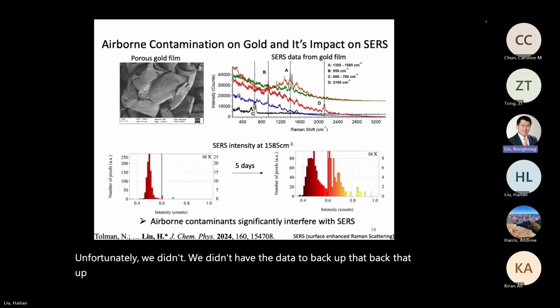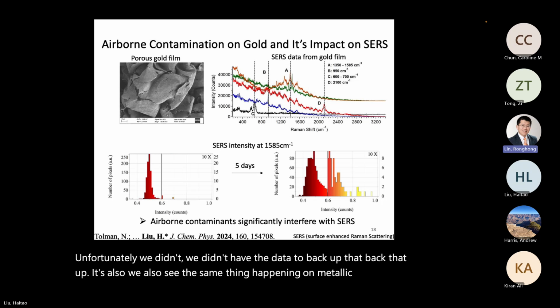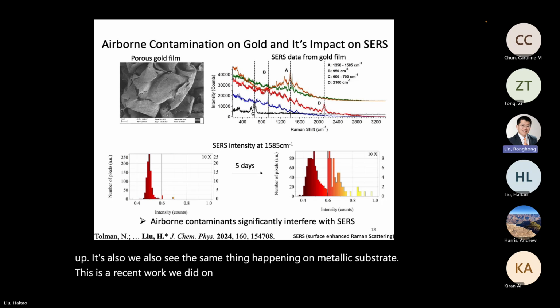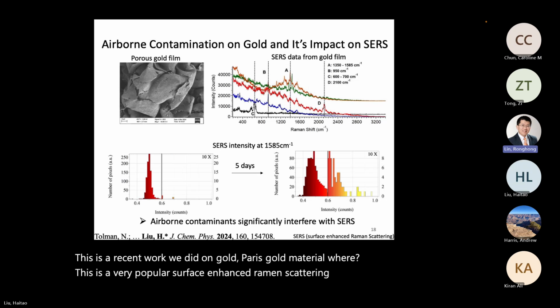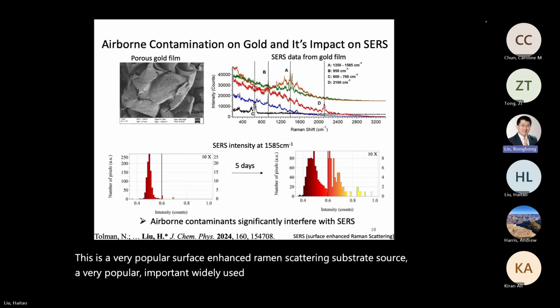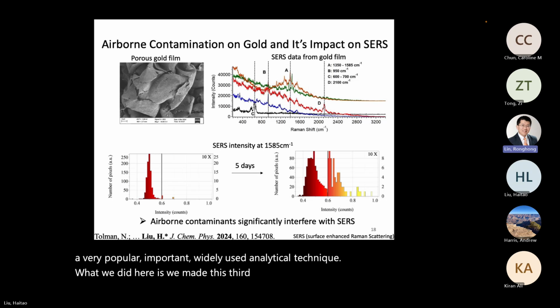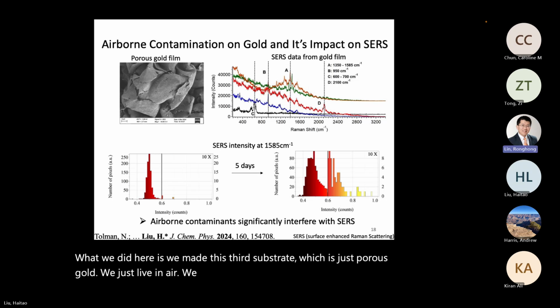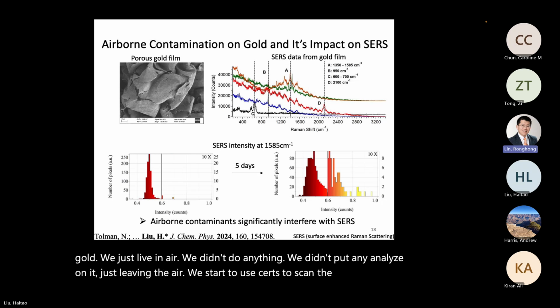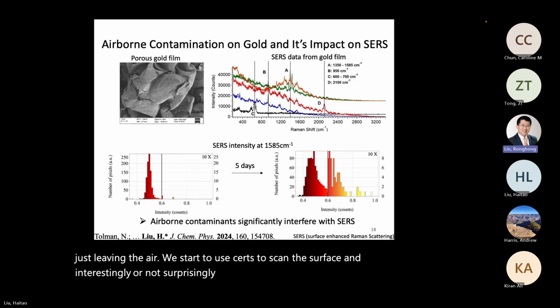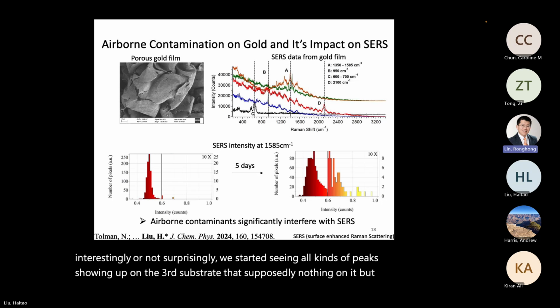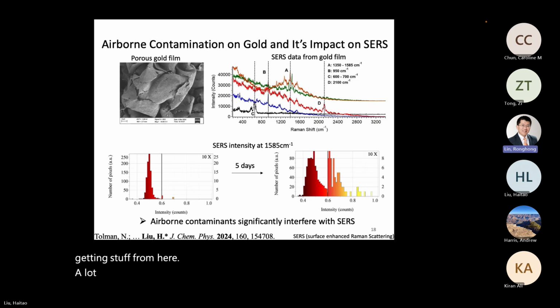Okay. We also see the same thing happening on a metallic substrate. This is a recent work we did on porous gold material, where this is a very popular surface enhanced Raman scattering substrate, SERS, a very popular, important, widely used analytical technique. What we did here is we made this SERS substrate, which is this porous gold. We just leave it in air. Didn't do anything. We didn't put any analyte on it. Just leave it in air. We start to use SERS to scan the surface. And interestingly, or not surprisingly, we start to see all kinds of peaks showing up on the SERS substrate that supposedly has nothing on it, but it's getting stuff from air. A lot of those peaks can be assigned, and one of those components seems to be related to amorphous carbon.